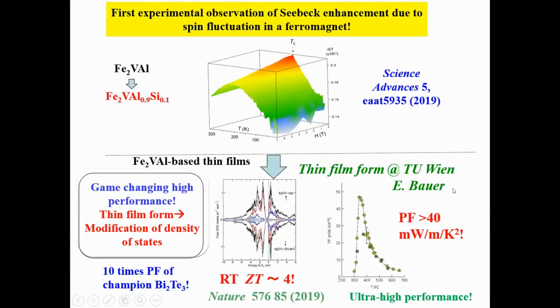And a collaborator in Europe, in Vienna, made these materials in thin-film form, and actually there appeared to be modification of the density of states, leading to a very high ZT, very high power factor, published in Nature. So these are some interesting developments found, especially in this magnetic semiconductor.